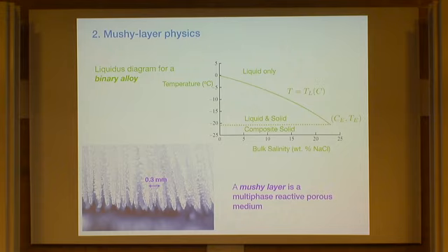So to discuss this picture again in light of this curve, if we consider one of the solid crystals here, that has a salinity of 0 and it's at some temperature. One of the things we're going to assume is that the liquid and the solid are at the same temperature, so there's a very high internal surface area, and the internal interfaces would grow or melt to achieve local equilibrium. So any liquid in the gaps would be at the freezing temperature.